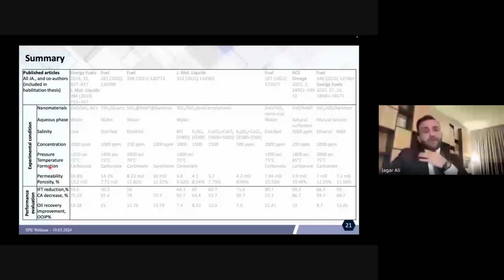So from this slide, we have the relative permeability shifting. Usually, as can be seen here, we use the experimental data obtained from the core flooding and use a software which is called CYDAR software. It works based on the JBN, which is the famous, well-known method for measurement of the relative permeability. And based on the result shown here for different nanofluids, it confirms that the wettability alteration is there. And with wettability alteration, we have different saturation levels, and then it shows a good and nice shift of relative permeability of water and oil from the right side to the left side, and it lowers the residual oil saturation.